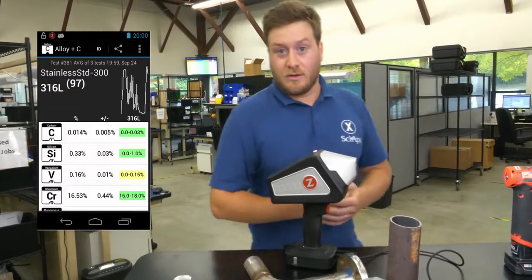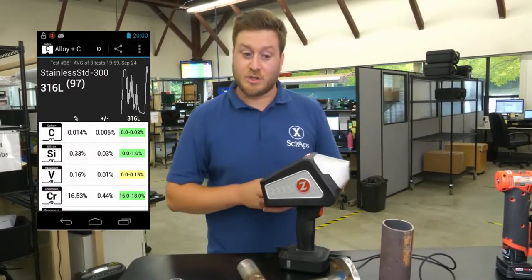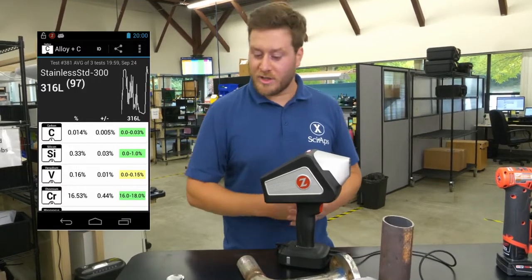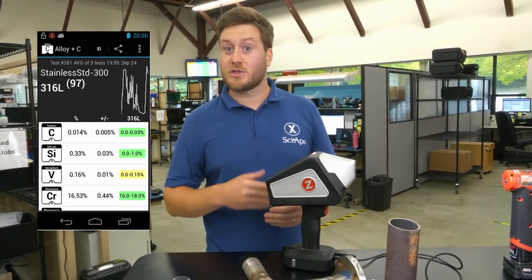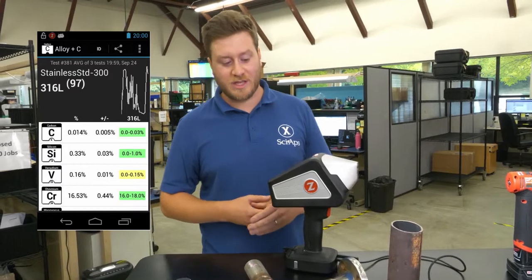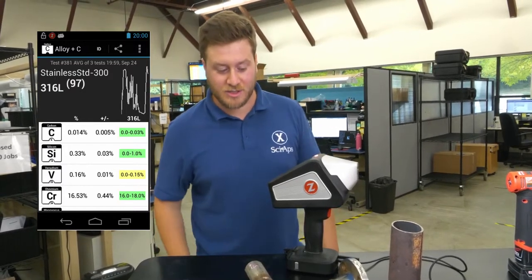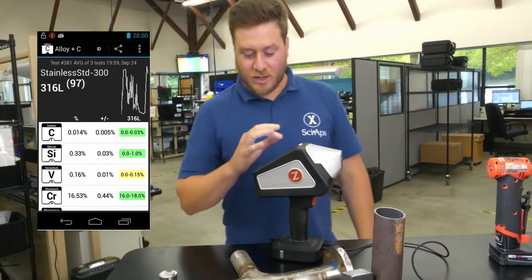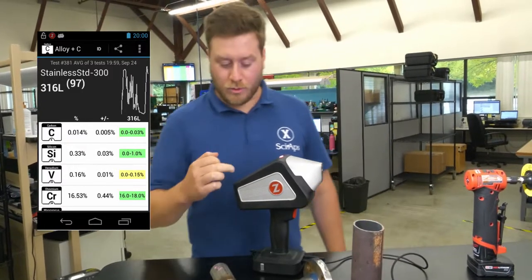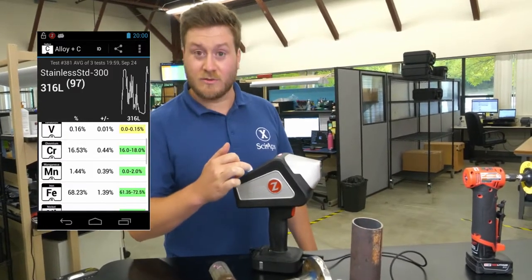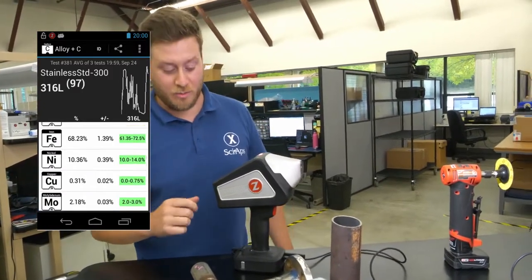As you could see there, the test actually runs through a pre-burn where it cleans the surface. Then it goes through and takes 3 different tests and averages them together to come to your final result, as you can see here. Comes up as a 316L due to that low carbon, and if you scroll down you can see the rest of the alloying elements within the sample.